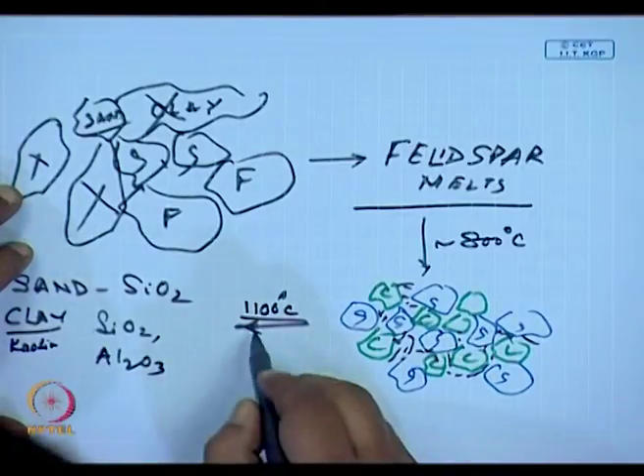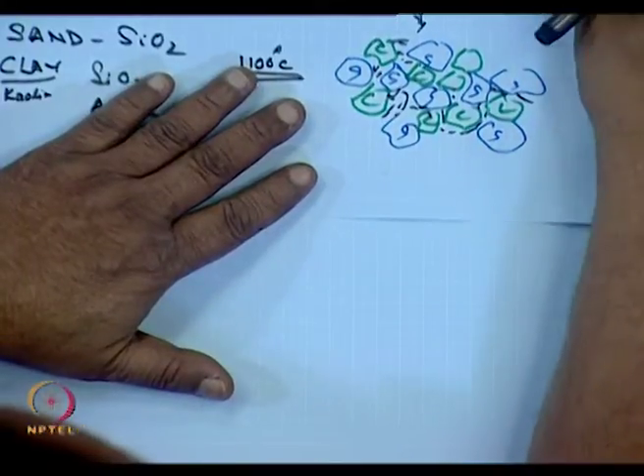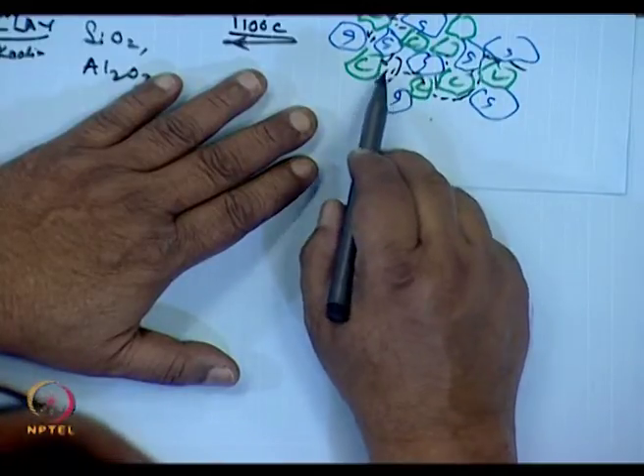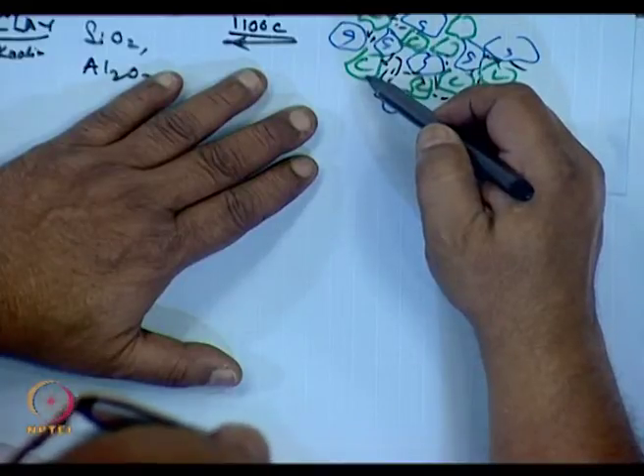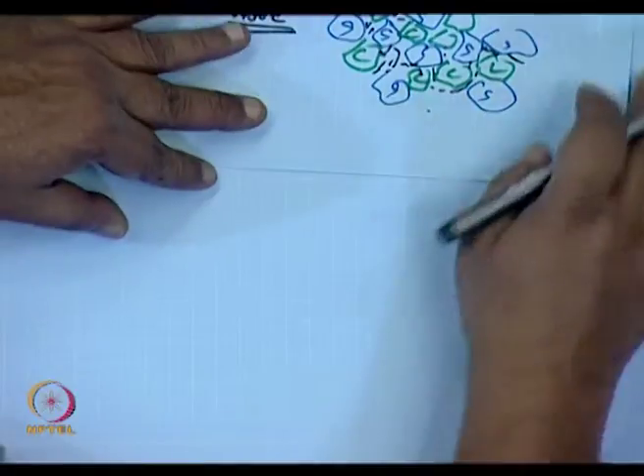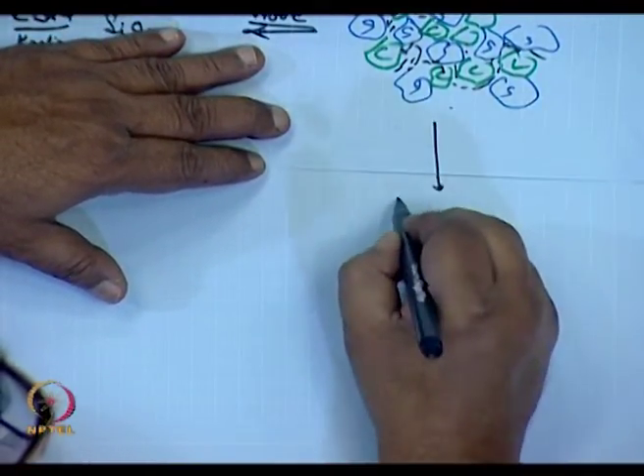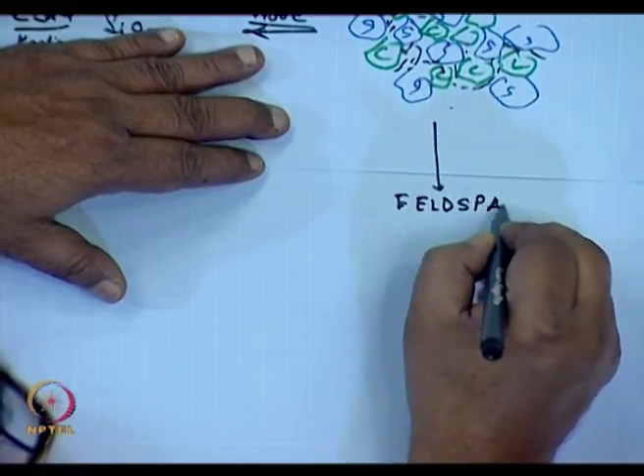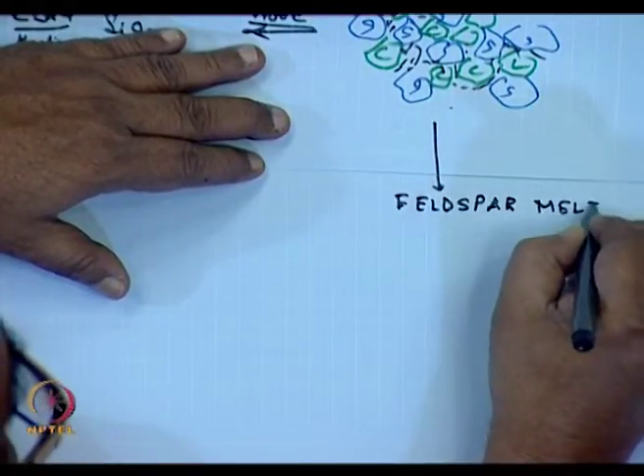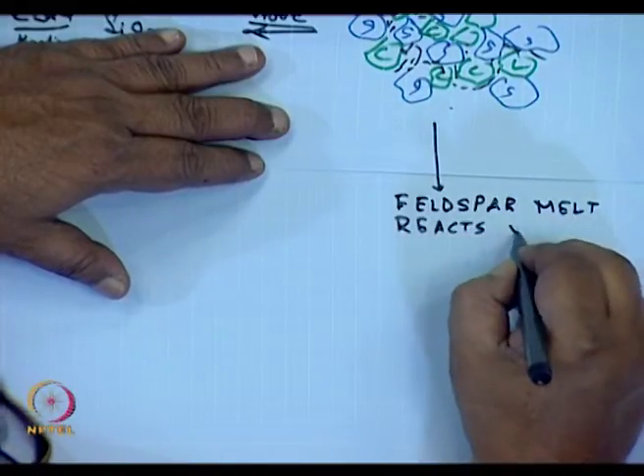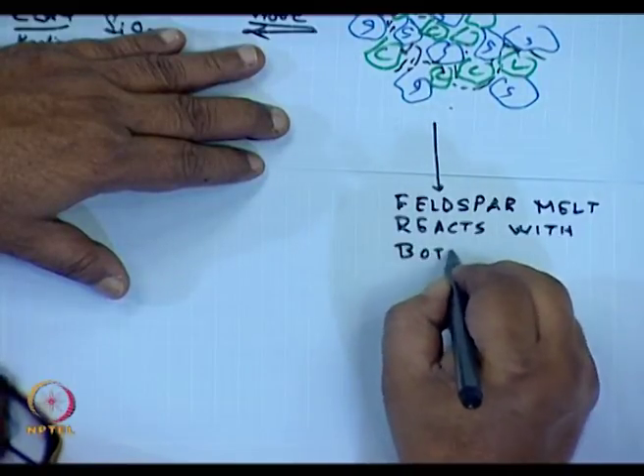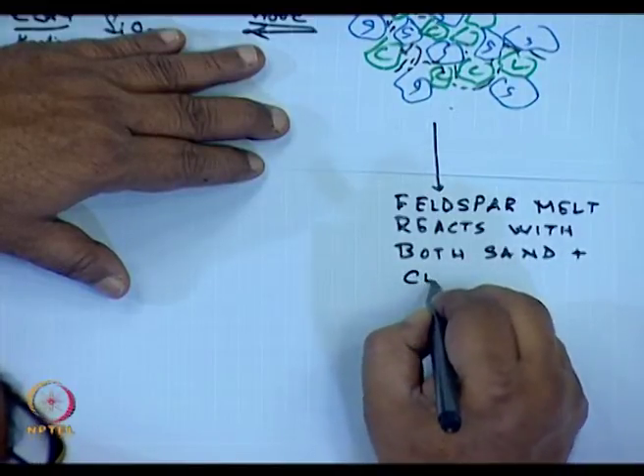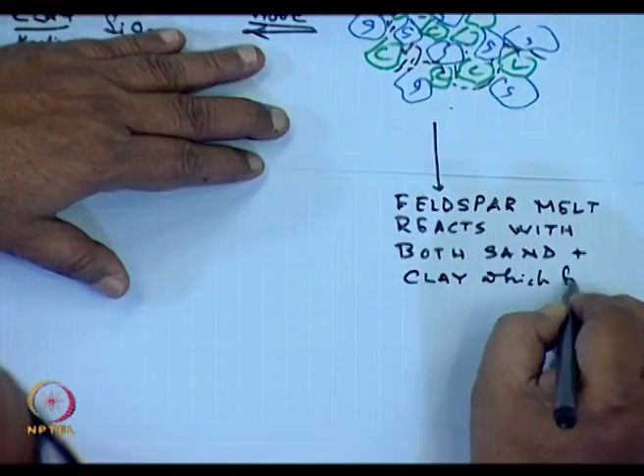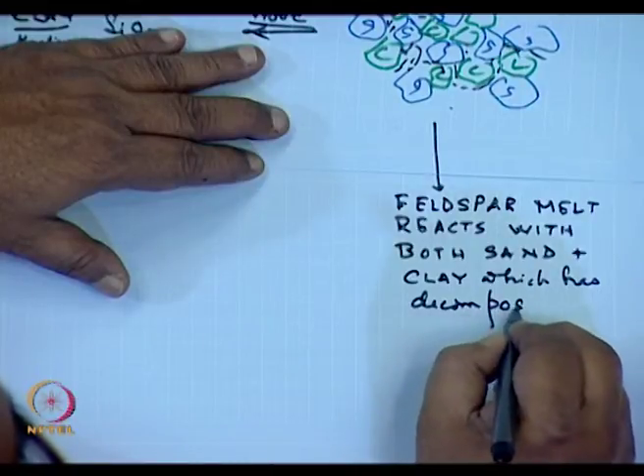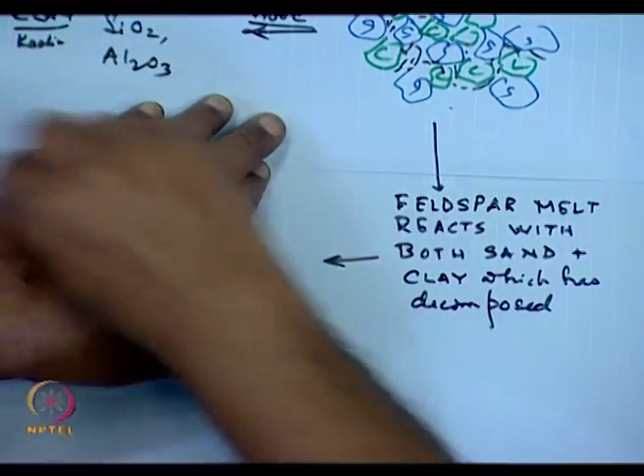What happens is this: now at 1100 degrees centigrade, if I keep it here, what happens? I have got the feldspar now coating the sand and the clay particles. The feldspar at this stage reacts with both sand plus clay which has decomposed. And this microstructure then changes to something like this.